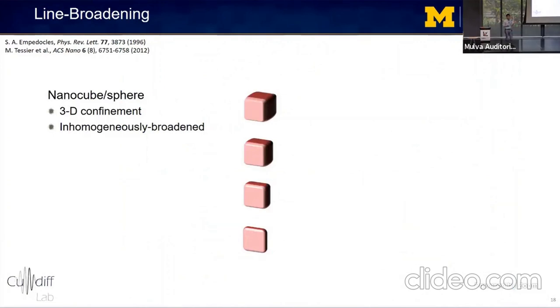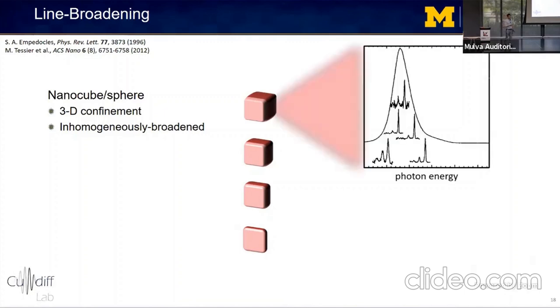So in nanocubes, excitons that you generate experience three-dimensional quantum confinement. So any variation in the nanocrystal shape or size is translated into a distribution of resonance energies. And the usual case where this resonance energy distribution is much larger than the line shape of a single nanocrystal is shown in the top right. And we call this line shape inhomogeneously broadened.